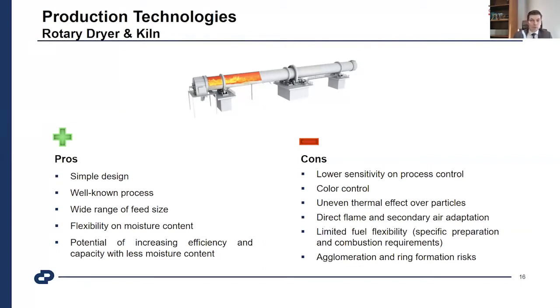And color control is another issue, because a direct flame is used in the rotary kiln, creating a reducing atmosphere, and it's a little bit complicated compared to other options. And because of the flowing bed of material, the thermal effect over the particles is not even, and that causes some particles to be crystallized while others are not fully dehydroxylated. It's an issue for the rotary kiln.